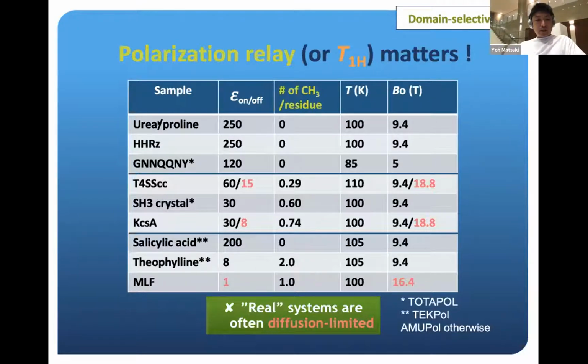Without methyl group here, like urea and proline, including hammerhead ribozyme sample, the enhancement is pretty high. But if you go to the regular proteins, even membrane proteins, which tends to be high in methyl group density, it is really coming down, especially at high field conditions. The effect is even starker with small molecule crystalline samples. If it is methyl loaded, the enhancement is very, very low because of this very dense molecular packing in the crystal. So this must be one of the reasons why we always see much smaller enhancement factor in real applications than urea or proline, meaning that those protein samples are a lot of times diffusion limited in DNP.